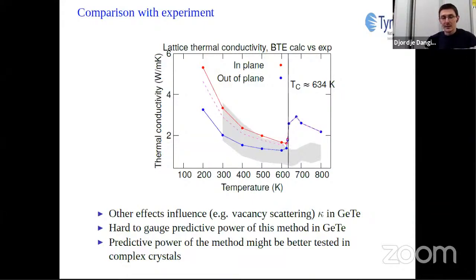We started this investigation because we wanted to make sure that our results for germanium telluride close to the phase transition make sense. And we already showed that, because the difference between the Green-Kubo approach and the Boltzmann transport equation approach is not very big. It's around 10%, which is way less than what you would expect from the variance in experimental results, which are shown in this figure here as the gray region.